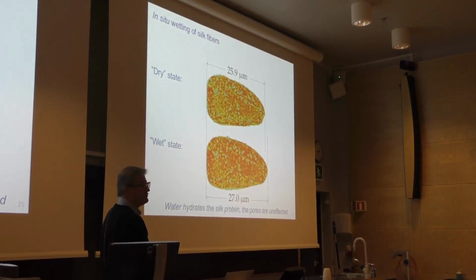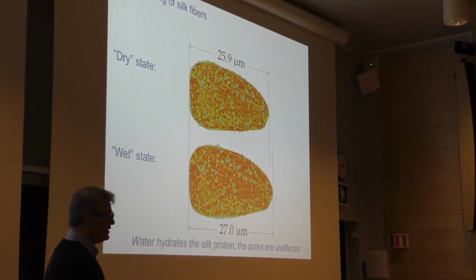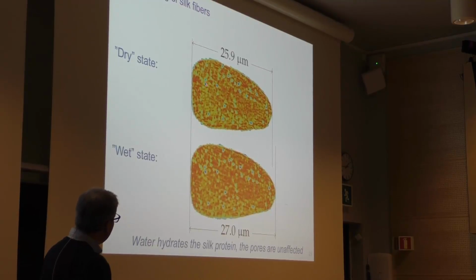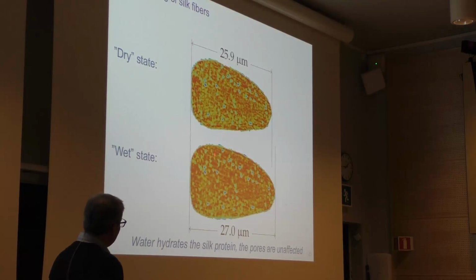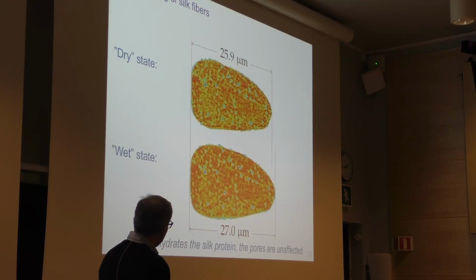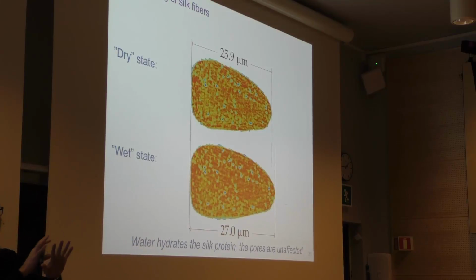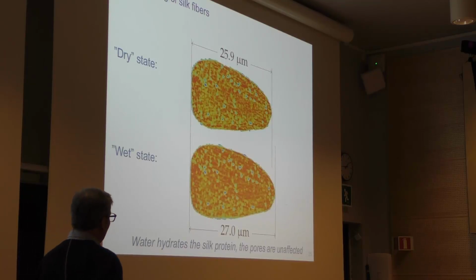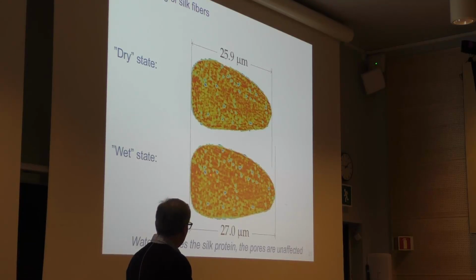But in addition, with this technique we are able to look inside the fiber while this is happening, right? So you can see that, and again to our slight surprise, we could see that these porous features that we saw inside the fiber here remain intact at the same places, which is evidence that the water which has been absorbed by the silk fiber doesn't go into those pores, as you would maybe intuitively have guessed in the first place, right? It rather goes into the hydrophilic silk proteins that are known to constitute the rest of the fiber here, right?